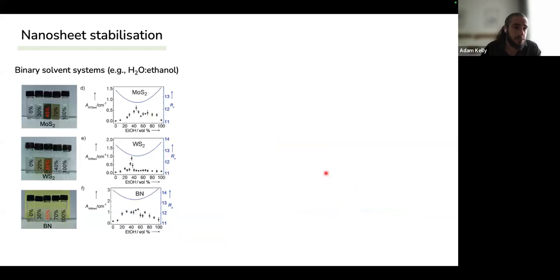So another way to do this is with a binary solvent system as well. So this gives you then tunability in surface energy because you can just mix in different amounts of, for example, water and ethanol. And it's funny, what we found was we read this paper where they found the optimum is around 40%. So 40% ethanol, 60% water. And we thought that this was pretty curious because I think we're all quite familiar with solvent systems that have 40% ethanol and 60% water.